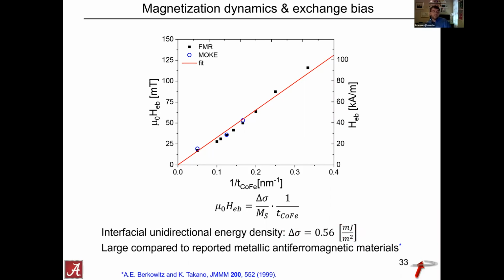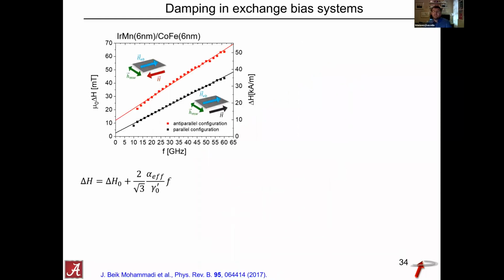And it turns out that for this system, it's very high, and it's much larger than most other metallic antiferromagnetic materials. And that's part of the reason why this system is so heavily used in applications. What else do we get? Well, the other thing we get from these measurements is the line widths as a function of frequency.